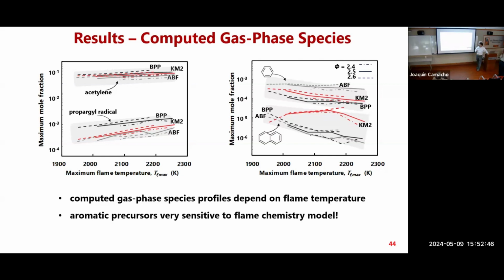For acetylene, for propargyl, it's not a stable species that we can measure. But for the gas phase species, it's a reasonable agreement. I should have presented it. And this is not a flame profile. It's like a summary of the max species at one max temperature. It's kind of like a global summary to plot.